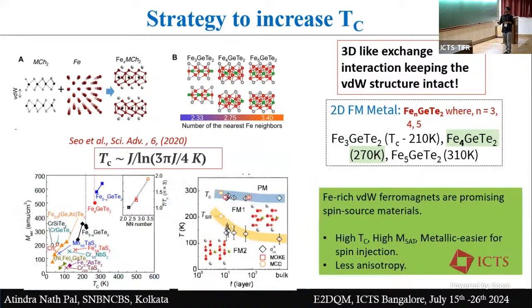Okay. With more background, they showed that if you increase the iron in the unit cell, which means you are increasing the nearest-neighbor iron-iron bonds, then you can see that the TC almost linearly increases. For example, F3GT has a TC of 210, with 3 irons in this case, and F5GT has a maximum of 310, with 5 irons. So depending on the nearest-neighbor iron-iron bond, you can increase the exchange interaction and enhance the TC, in spite of the fact that all 3 have different crystal structures.